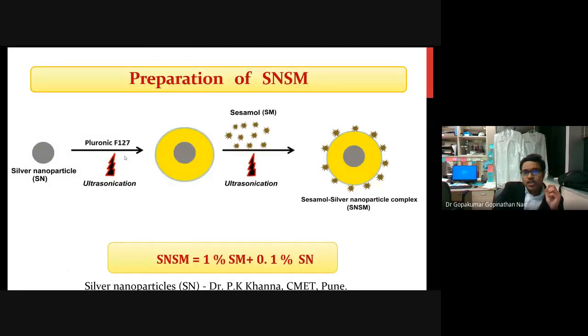And we have used silver nanoparticles obtained from Dr. Khanna. And here we have used a non-ionic surfactant emulsifying agent, that is pluronic F127. Using ultrasonication, we made the pluronic silver nanoparticle colloid suspension, and drug was added at 1% of SM and 0.1% SN nanoparticles to obtain the sesamol silver nanoparticle complex.